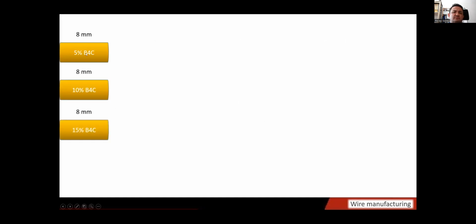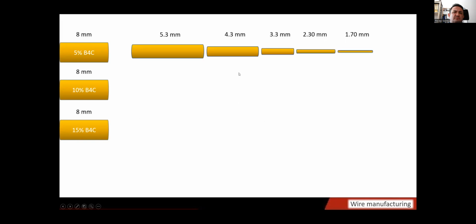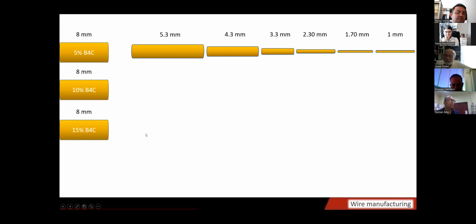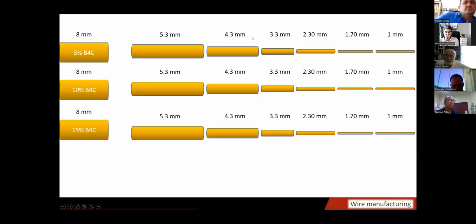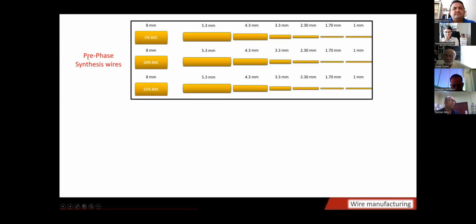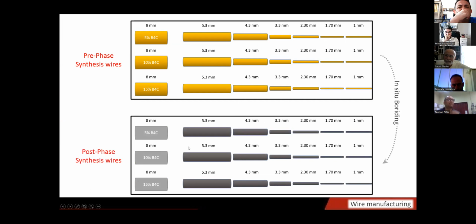So, summary: 8 millimeter wires filled with 5, 10, and 15 volume %. You go down, increase the deformation level. You have these type of wires, and then for each set of reinforcement ratios, you have this many wires with you. Then these wires in the pre-phase synthesis state, because there is no heat treatment applied on them yet, are subjected to in situ boriding, and then you get another set of wires, which is believed to have iron boride phases inside them, and then you have all these parameters which you need to investigate about these wires. Influence of deformation level, influence of increasing reinforcement ratios in the pre-sinter state, and then again information of influence of deformation levels on the borided regions, and influence of increasing reinforcement ratios on the borided regions in the post-sinter state.